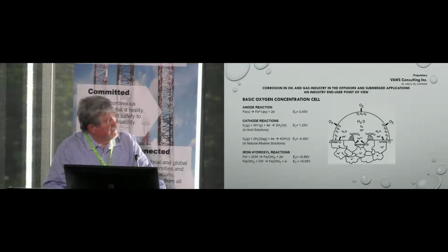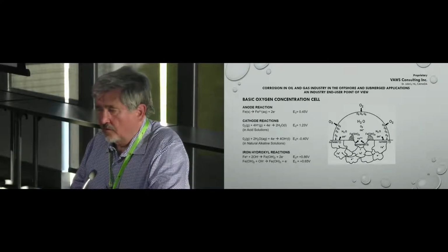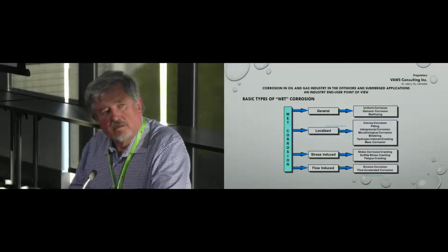Here are some reactions which are associated with the process, and they are important, especially the voltages which are occurring there. On the bottom, second line from the bottom is 0.86 volts, which is needed to stop the cathodic and anodic processes and protect the metal by cathodic protection.